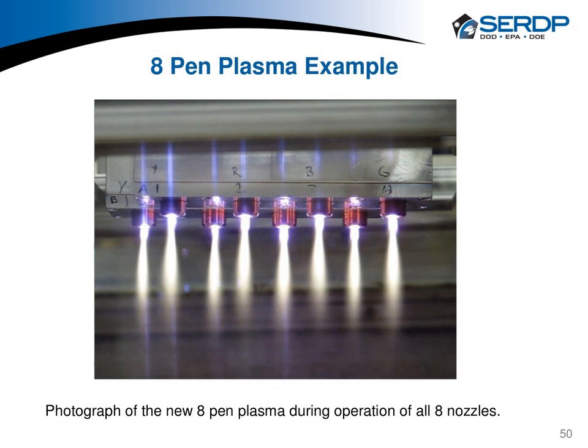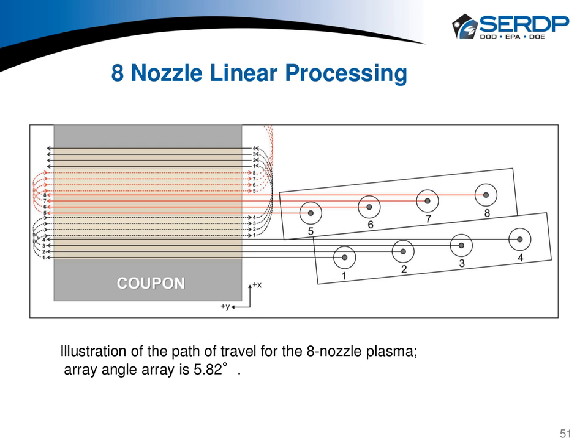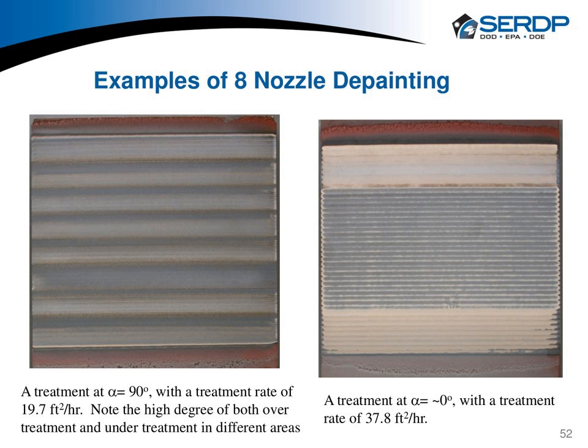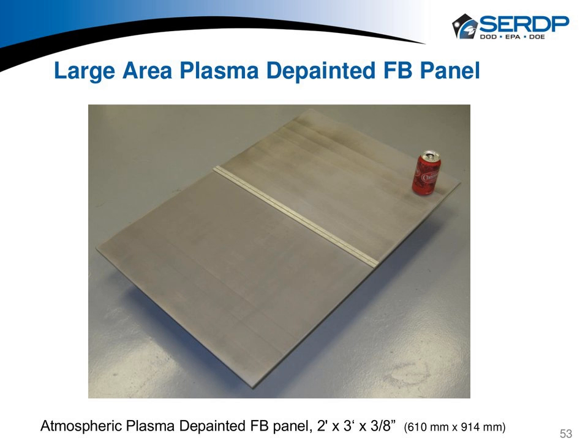Moving ahead, here's where we ended up in the project with 8 nozzles, but this could easily be replicated to whatever number one desires. There are some slight differences in the way that the 8 nozzle is rastered over the surface because of the geometry. I want to show one example here of the 2 extremes, where the 2 modules are at 90 degrees versus at 0 degrees, a single pass. Clearly these aren't ideal, but that's what you get in a single pass. This is much better. I think everyone agrees, and this is what we're after, and that's what we achieved upon scale up.